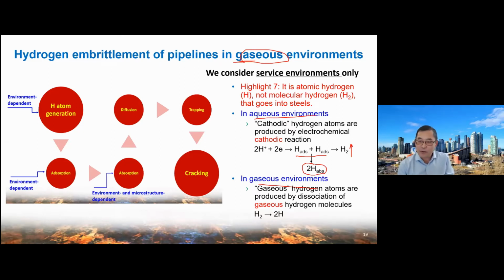In general, if hydrogen is produced in a solution environment, only roughly 10% of the ADS goes into ABS. That means 90% will become hydrogen bubbles and attach on the steel surface. So this is the solution environment. For the gas phase, the hydrogen will decompose from the H2 that we carry, the hydrogen gas H2. Decomposition of H2 produces H, then the H will go into the steel. So you can say the generation of hydrogen atoms is totally different.